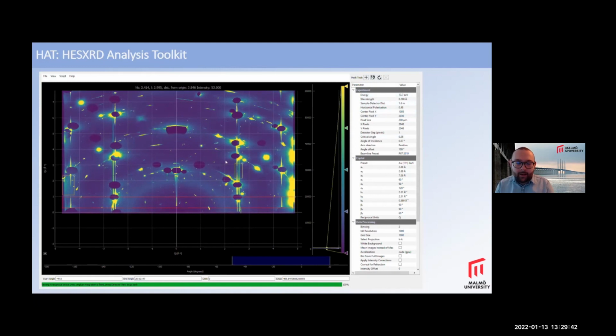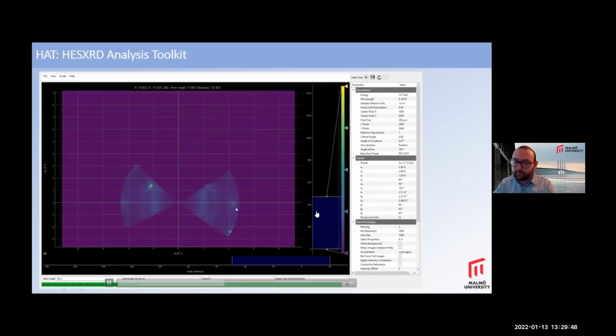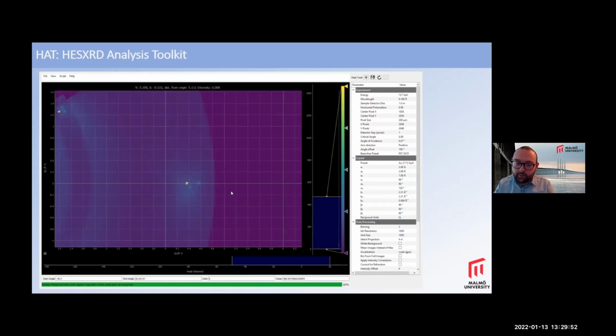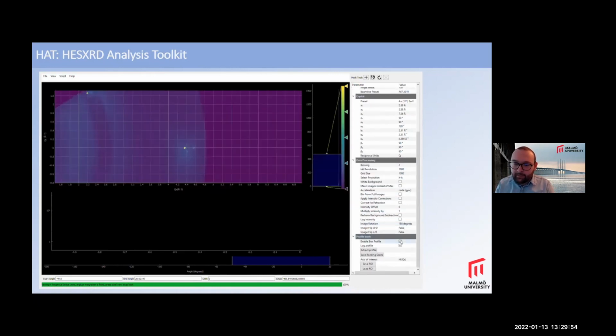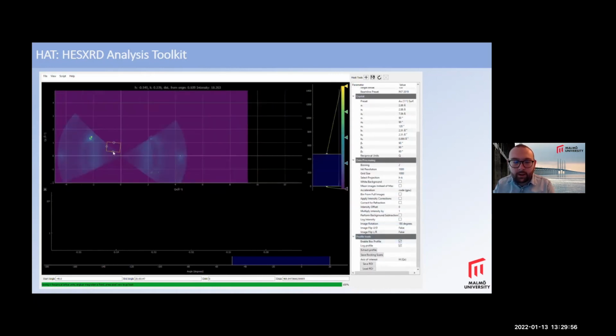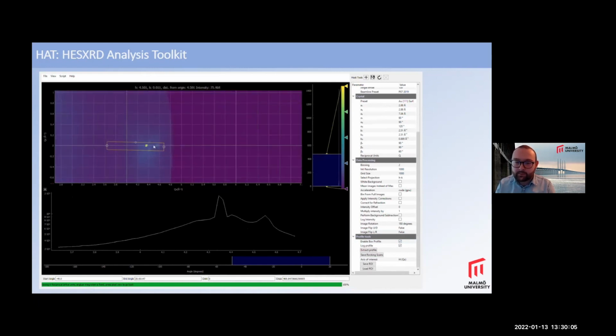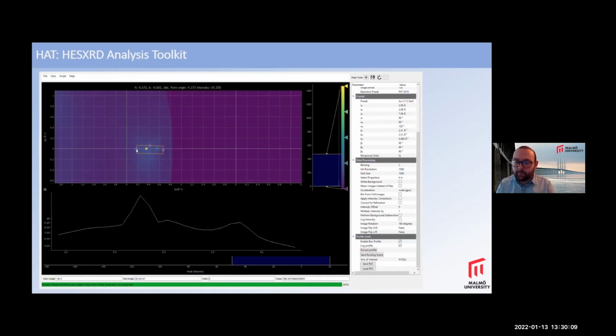And then in the background, it's converting this into a reciprocal space map. So you can choose a projection to include those pixels in. And then we have this reciprocal space map. We can take line profiles across this. So this is the equivalent of your in-plane scan in normal surface diffraction. And you can really play around with the data and see what you actually have.